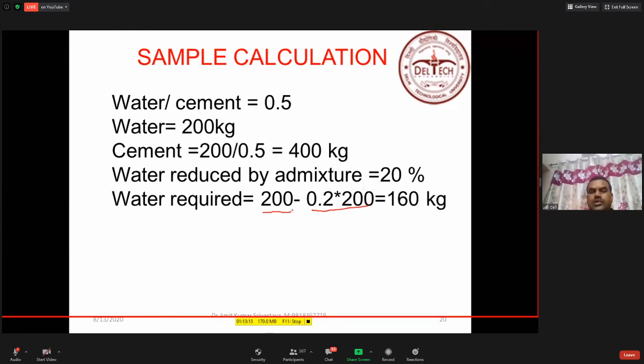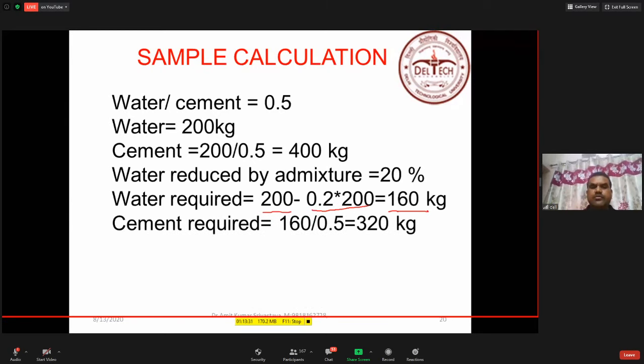So now if I see the water reduction is 20%. So now if you see this calculation, water required is 200, reduction is 20%, so minus 0.2 into 200, so it is 40, so 200 minus 40 is 160 kg. Now, see, if I use a chemical admixture which is reducing the water by 20%, the water required will be reduced to 160 kg, and for the same water cement ratio of 0.5, so water is 160 kg, water cement ratio is 0.5, now the cement requirement is what? We got the cement requirement as 320 kg.